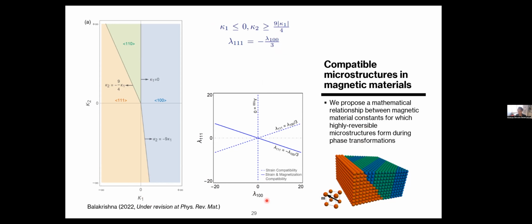If one is looking to change the alloy composition to develop these alloys, this would, for example, be a potential guideline to search for alloys that can be transformed, or which are highly reversible and can be transformed from the paramagnetic to the ferromagnetic phases with minimum hysteresis loss.